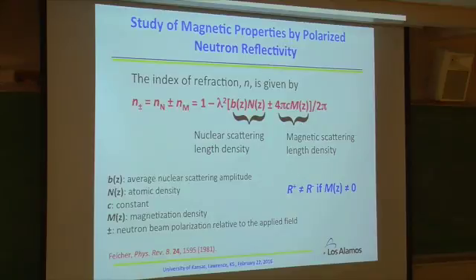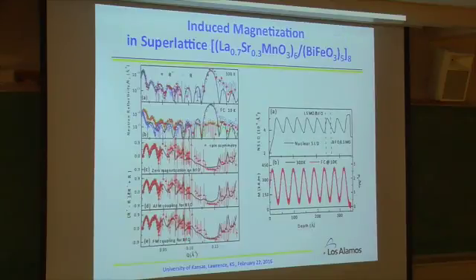So the way we did it is, since this is really a thin film, the neutron is mostly applied to bulk, right? For thin film, we are talking about a centimeter square substrate. The reason is that for the reflectivity measurement, you need a large sample. Otherwise, you will not have a strong signal. So you have to have at least a centimeter square. It's not a silicon technology, but you are still talking about a centimeter square substrate with quite uniform properties, right?